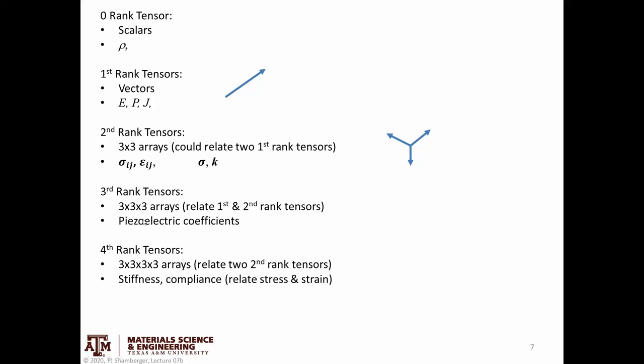But we can scale up even further. So piezoelectric coefficients have to relate a first and a second rank tensor. And so in order to do that, you need a 3x3x3 array. That means 27 different elements.